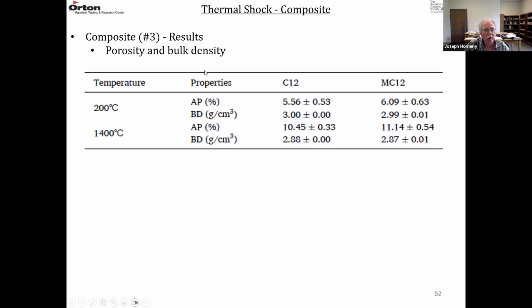So this is the porosity and density. AP is the apparent porosity, BD is the bulk density. This is the curing temperature, 200, and this is the other curing temperature, 1400 degrees C. So C12 and MC12, both 5.5%, 6% porosity at 200. And then the bulk density is basically the same, about 3 grams per cubic centimeter. And then at 1400, the porosity, this is 10.5, this is 11, they're almost identical, and the bulk densities, 2.88 and 2.87, are almost identical.